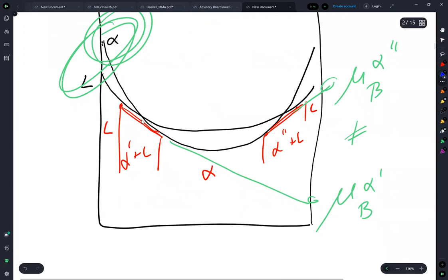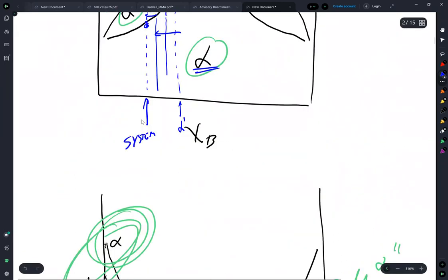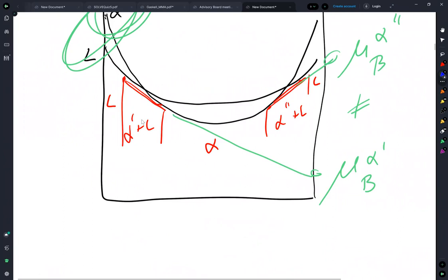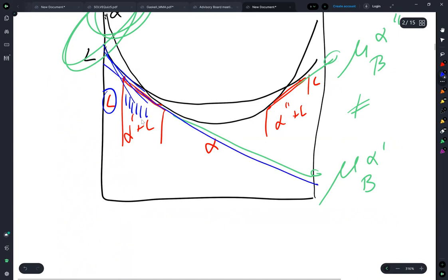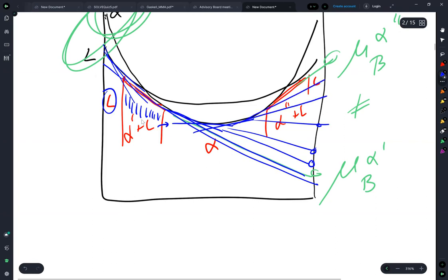And we know it's going to have the same chemical potential because instead of varying the temperature, we could say, well, what happens if we vary the composition? And we know that over in this liquid region, the chemical potential is defined by the slope. You reach the common tangent line, and as you move across the common tangent line, well, it is now fixed constant. And as you cross from the alpha prime to the liquid, it stays constant right at that line, but then continuing into the alpha, now the tangent and therefore the intercept changes until we reach the alpha double prime.